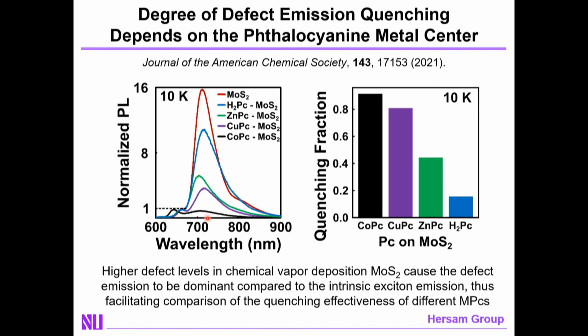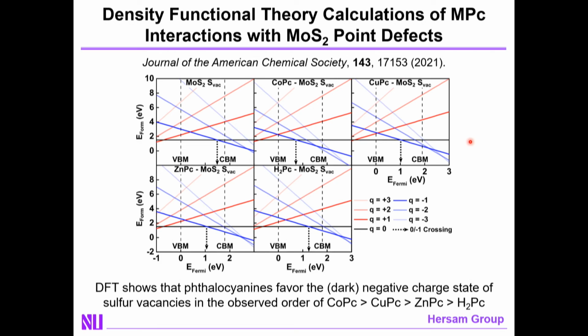In any event, a question then arises, why does this depend upon the metal center in the phthalocyanine? So again, we turn to Pierre Darancet at Argonne National Laboratory. He looked at what charge state should be preferred for the most common defect in moly disulfide, namely sulfur vacancies. He found that the negative charge state, which is the dark state, in other words, the state that does not emit light, is favored in the observed order ranging from cobalt to metal-free phthalocyanine, in the same order that's observed experimentally. So this is a case where the interaction between the 0D component and the 2D component of the mixed-dimensional heterojunction is influencing the charge state of the point defects in the 2D system, thereby allowing you to quench the undesirable contributions of those defects.